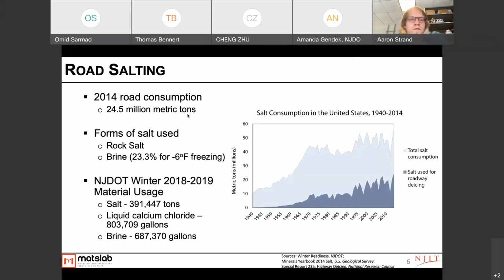These surface applied chlorides are typically from road salting. In 2014 in the United States, 24.5 million metric tons were used just for de-icing of our roadways, which is a large percentage of our total salt consumption. As the years have gone on, we continue to increase the amount of salt that we use for de-icing. The forms of salt used are typically rock salt or a brine, which is typically about 23% and drops the freezing temperature to about -6 degrees Fahrenheit. More recently from NJDOT, in the 2018 to 2019 winter, about 400,000 tons of salt, 800,000 gallons of calcium chloride, and about 600,000 gallons of brine were applied on the roadway in just that one year.